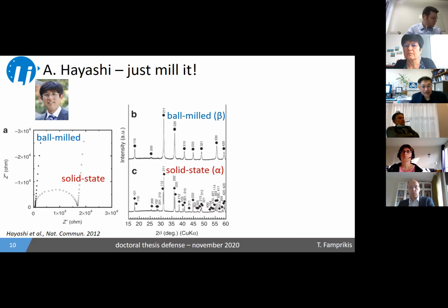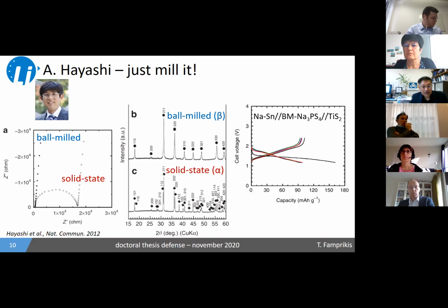They showed that the ball mill material actually exhibits the beta phase, so the high temperature phase, stabilized at room temperature, in contrast to the alpha phase, the tetragonal phase that you get from a typical solid state synthesis. And they hypothesized that this is the reason why we see such a high conductivity. They use this material that now has a usable conductivity to demonstrate the first working sodium batteries based on Na3PS4, shown on the cycling here.